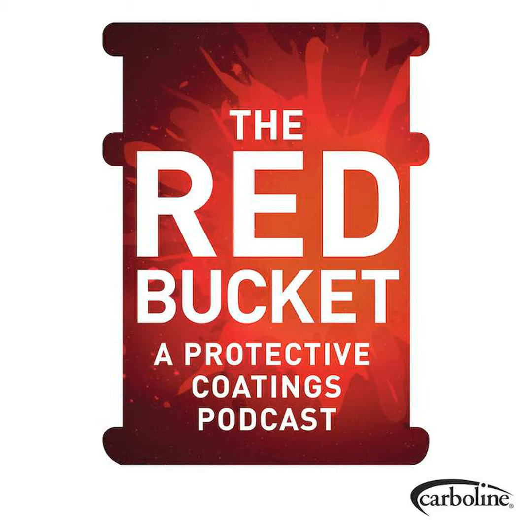Intermediate layers. Typically on tanks like this, intermediate layers are usually more of the aliphatic polyurethane type. So we can add some build to the system. We can add some additional chemical resistance, but it's not to say that an intermediate coat cannot be an epoxy. Again, another barrier coat to add some mils to the system to provide that enhanced barrier protection with a normal aliphatic polyurethane, and then obviously a top coat. So the fluoropolymer top coat providing the UV resistance, the excellent color and gloss retention, in addition to the chemical resistance that this resin in this system provides. So it's like building a house. Use your primers as your foundation. You're using your intermediate coat or coats as the framing of the house.